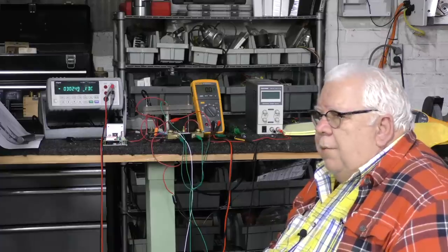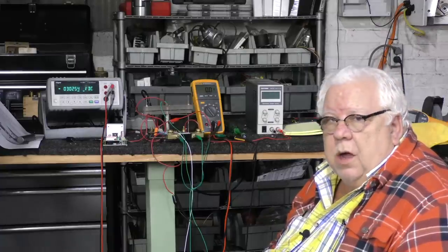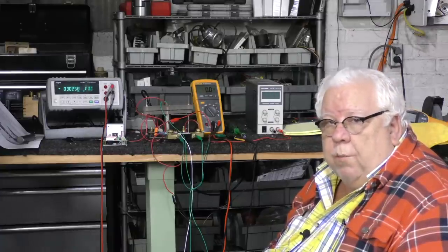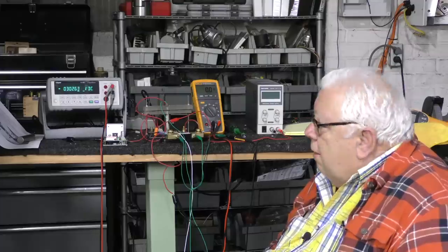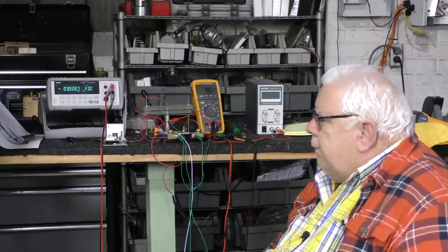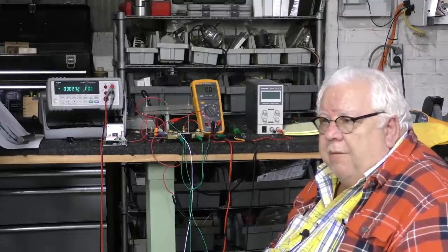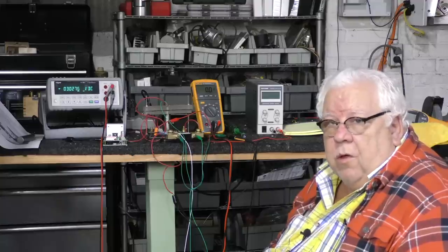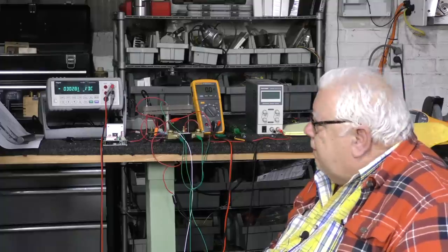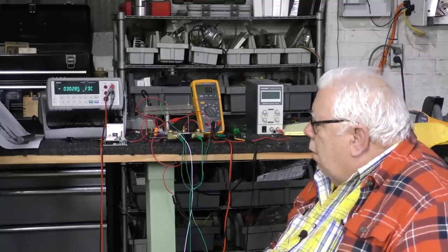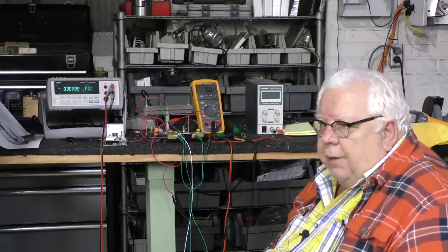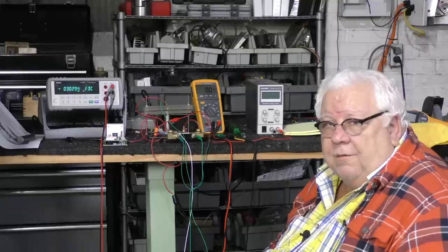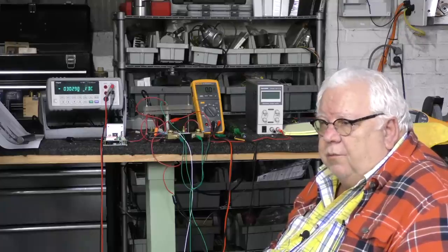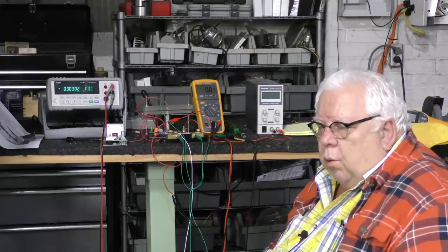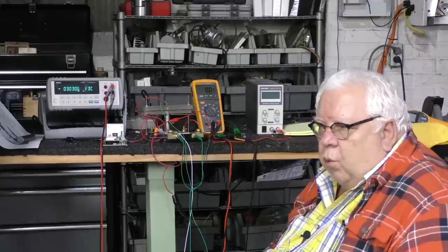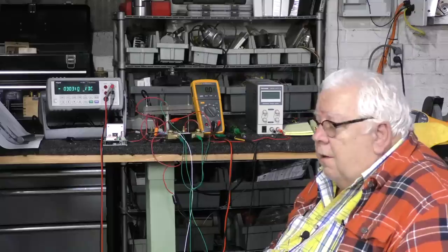Now, in automated equipment, you simply set a value, a cutoff. If they're going from 4.3 to 2.8 at 0.1, they're being very generous to themselves on an amp hour measurement. Consider this a more real-world use of the battery capacity analysis, where we've tried to match it to a real-world scenario. Now, driving around in town, we can't do that very easily.